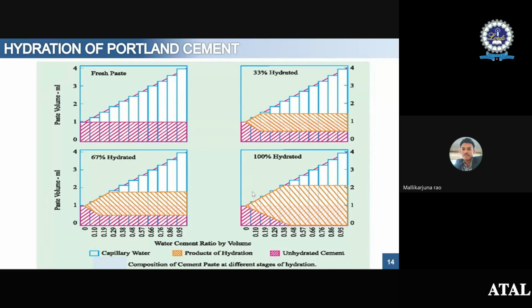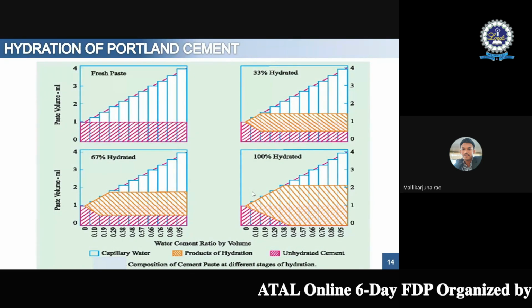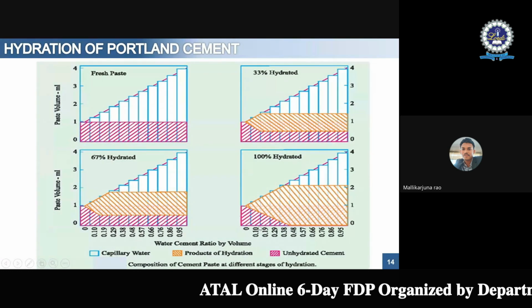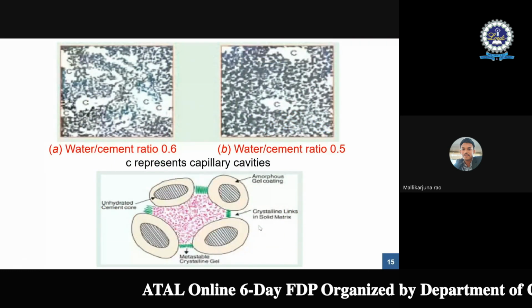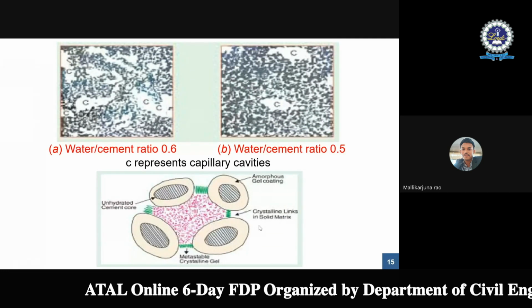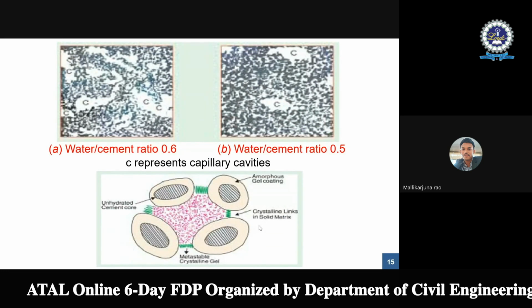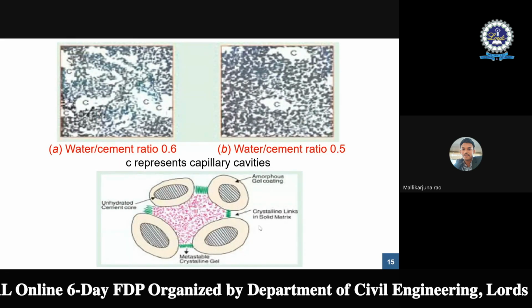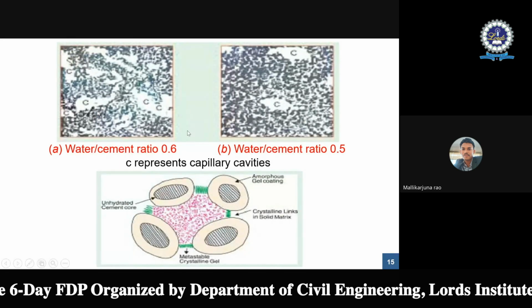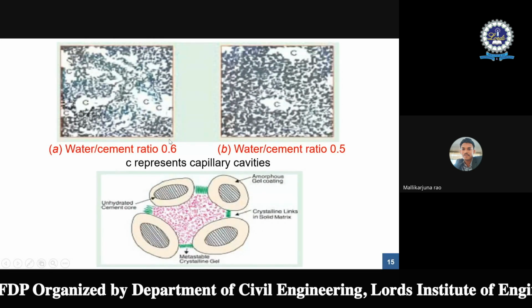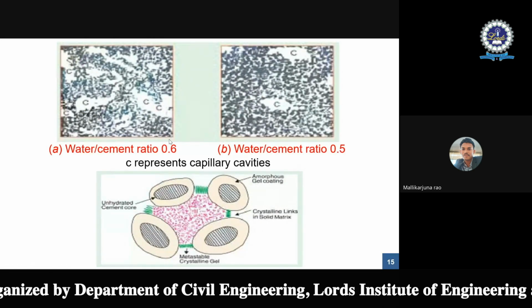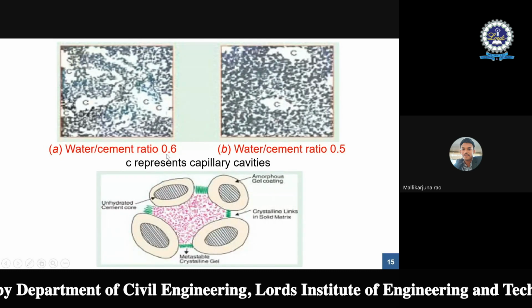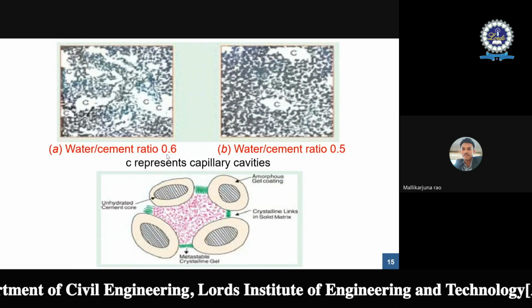So here we can see a certain volume where you had the fresh paste, and after 33% of the hydration, slowly the amount of hydration continues, and the unhydrated products get reduced there. And here you can see the difference between the two water cement ratios we considered. One is 0.5 and the other one is 0.6, where your capillary cavities are there. Based on your water cement ratio, the amount of the gel formation would vary, and the strength contribution is also going to be reduced through a high water cement ratio there.